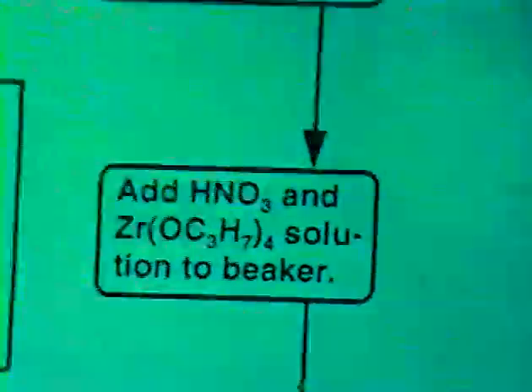And finally, by allowing the gel time to go even longer, to a minute or more, we also grow much larger particles, and at the same time, by allowing the particles to grow more slowly, in a sense, it's a low temperature way to anneal out the defects. We found that these particles actually resist the tetragonal to monoclinic transformation better, even though strictly on size alone, there's no large difference in size between these two particles. So I think what I have shown is that by controlling gel time, we have an interesting way to control not only the particle size of the material coming out of the solution, but also the quality of the particles in terms of defect densities.